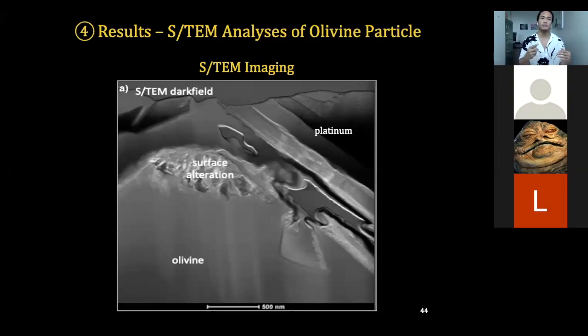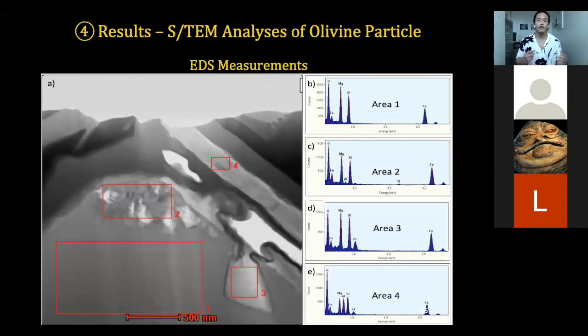We wanted to do EDS measurements of this to look at these alteration and surface features to see if they may be chondritic. As far as EDS measurements go, we took measurements in 4 different areas of that portion of the sample: areas 1, 2, 3, and 4. Area 1 has a spectrum that is consistent with an olivine particle, and that's similar to area 3. However, the main difference is area 3 is a thinner section of that olivine, probably due to some mistake during the thinning process. It also has some platinum contamination, most likely because of the platinum that we deposited on top when we were preparing the thin section. Area 2 is consistent with an olivine that has been altered and is morphing into a clay-like particle. And then the spectrum for area 4 is consistent with a clay-like material, and that is probably, again, that surface material that was on top of our sample.